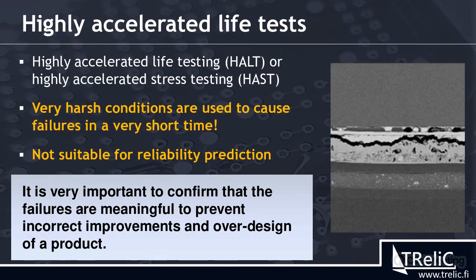It is, however, very important to notice that from time to time these tests can accelerate failures which are not meaningful and lead to incorrect improvements. So meaning that you over design or change something which would not need to be changed. So this is something which is good to understand. So HALT testing uses temperature, vibration, and humidity, while highly accelerated stress testing deals with very high temperature and humidity. But I've seen both used very successfully. So they are also used, but you need to be careful when you're using them.